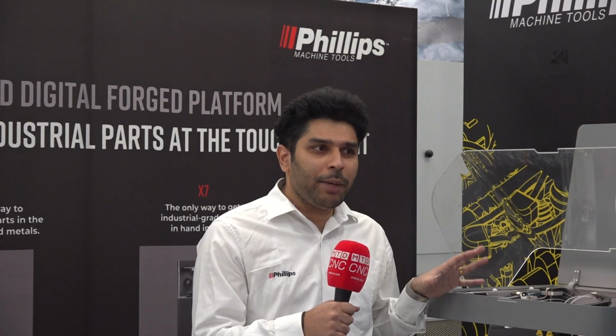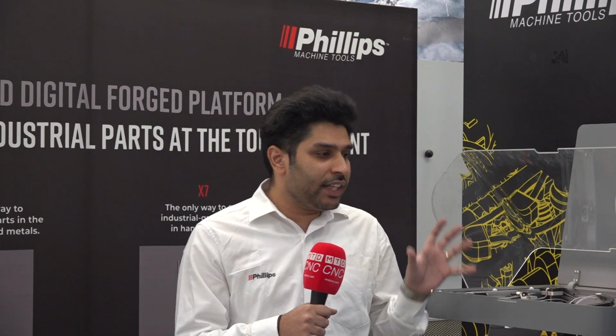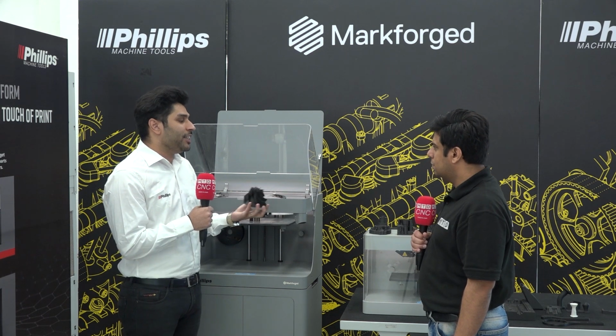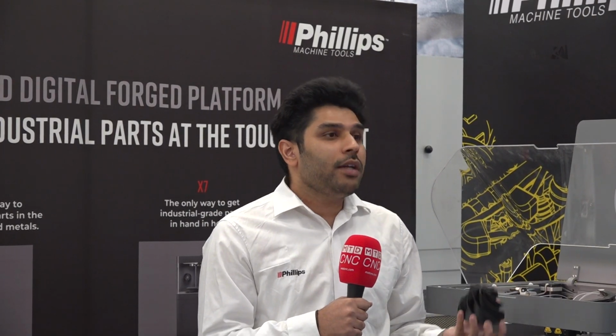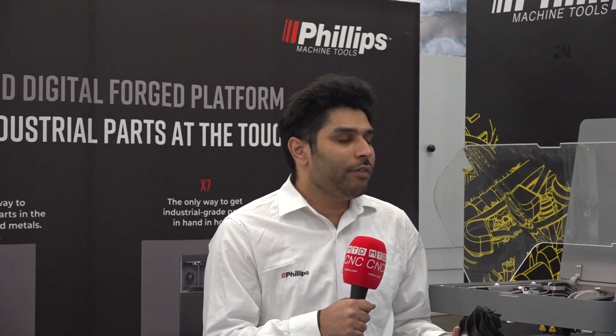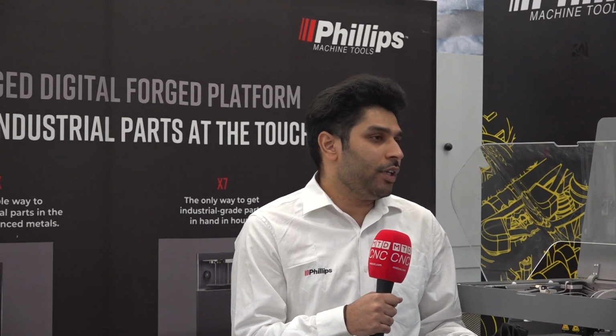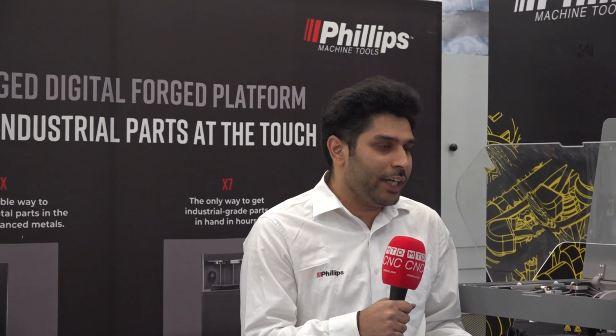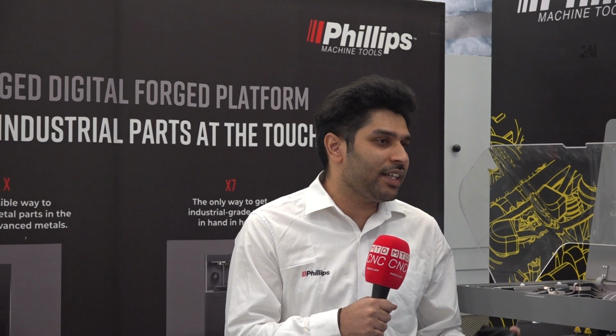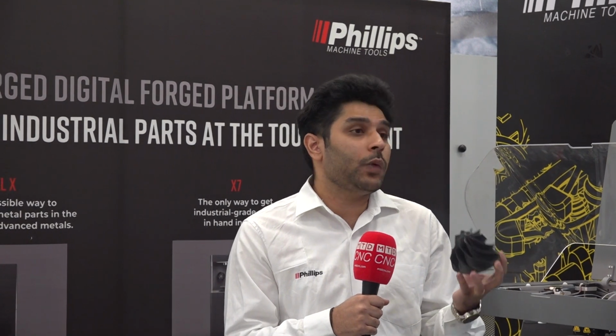As we know, a printer can print a part, but imagine a printer which is printing the part and at the same time even scanning the part. Once the part is ready, let's say the particular part is prepared, you get it in your hand, you will also have data which tells you the CMM report of this part. Suppose I feel the CMM report is not as per my requirement, it is having a deviation of around 100 microns, which is what a 3D printer can provide, and we need an accuracy of, let's say, 20 microns, which is not directly possible with any 3D printer. So what we do is, we have a software called Blacksmith. We tell the software to recorrect itself and print the part again. After 2 or 3 trials, we get the same part with an accuracy of less than 20 microns.